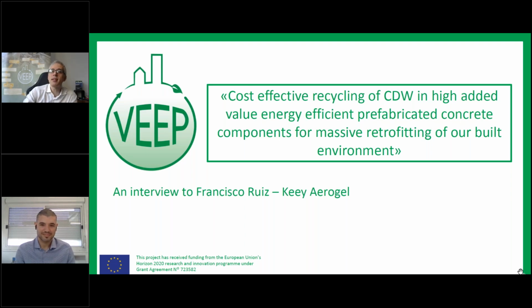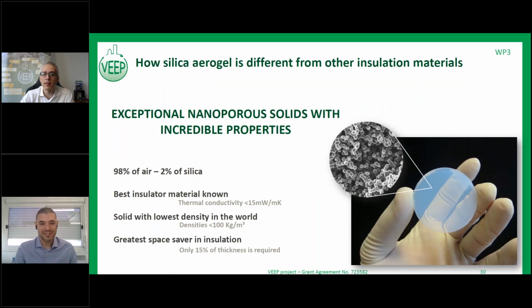Francisco, can you please tell us more about this silica aerogel? What differentiates it from other insulation materials? Thank you, Alessio, for the introduction. So aerogels are an exceptional nanoporous solid composed of 98% air and only a very little 2% silica. Due to those properties, aerogels are the best insulator material known, with thermal conductivities below 15 milliwatts per meter per Kelvin. Today, compared with other insulation materials, we only need 15% of the thickness of the insulation for the same thermal performance.